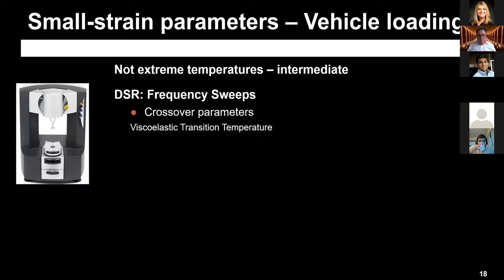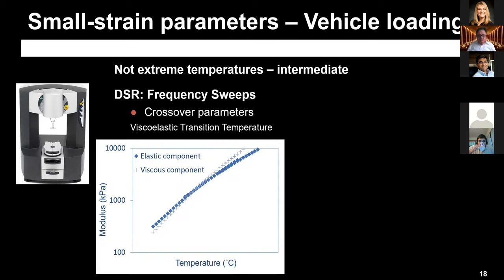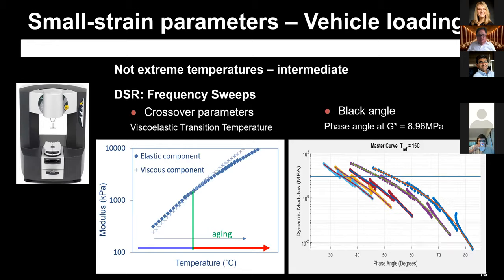The frequency sweep testing provides the small strain parameters that relate more closely to vehicle loading and are tested at intermediate temperatures. The crossover parameters provide the viscoelastic transition temperature. And as you can see, those increase with aging. The master curve is shown on the right-hand side of the slide, and it shows the G-star at 8.96 megapascals, and that is used to characterize the phase angle. And you can see those decrease with aging.